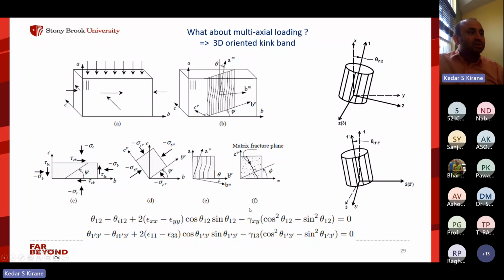And the other thing to consider here is that if there is compression transverse to the fibers, then there is a transverse compressive failure whose mechanism is different from kink band formation. That is purely matrix shear failure. So that has to be incorporated on top of the kink band formulation. So this is what we are currently working on, but it is a work in progress, not complete yet.